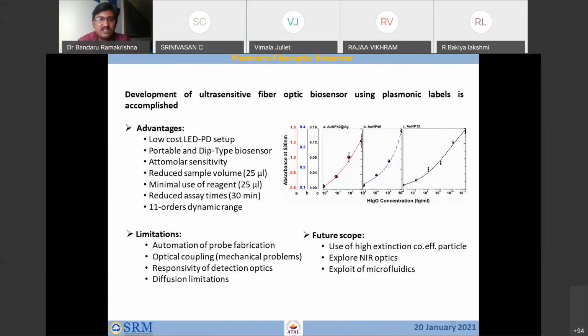This is very, very important research that we have carried out, and you see that the total advantage here is we are going to do analysis without a spectrometer. Here you don't need a spectrometer because we are not looking at the spectral shift. We are only looking at the absorption, which means only one wavelength, and how much the intensity varies. So it doesn't require a spectrometer, so we can go with a PD, which reduces the cost of your diagnostic procedure, because a spectrometer is costly equipment. Only a small LED, a PD, a small fiber and a little amount of nanoparticle solution is enough to carry out this entire work.